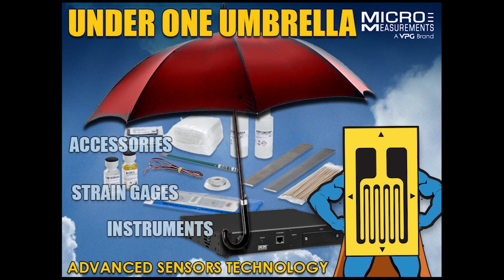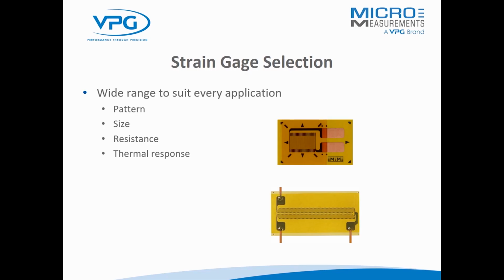So this next slide shows two different strain gauges for two different purposes. The first one is one of our newest CEA series gauges, and if you look at it closely, what you'll see is that the tabs are off to the right side. We do this because this gauge is really intended to be used on a compression test of composite materials, and there's a very small half-inch long window to get the strain gauge installed and to get the wires out. So what we found is that it's a lot more convenient to put the tabs on the side as opposed to in line with the gauge, and that allows our customers to take the wires out the side as opposed to being in line with the coupon that sometimes can interfere with a fixture.